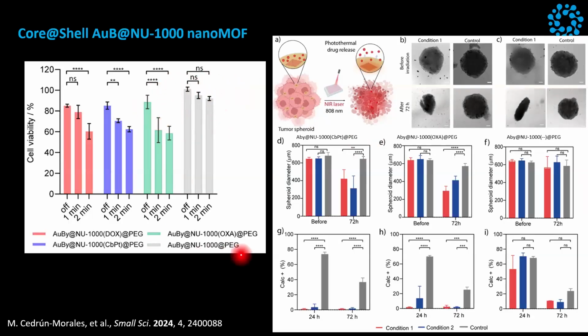Okay, this is the control. It's the particle without anything inside. So nothing happens. You look at 24 hours, 48 hours, and you see that with this irradiation, very low irradiation, you don't kill the cell because you don't produce enough heat to kill the cell. Because what I want is that what produces the cell death is the release of something that is a drug that is used in the clinic, doxorubicin or carboplatin or